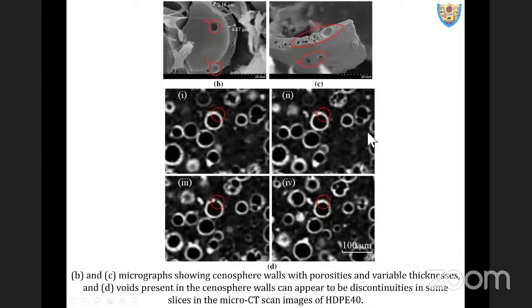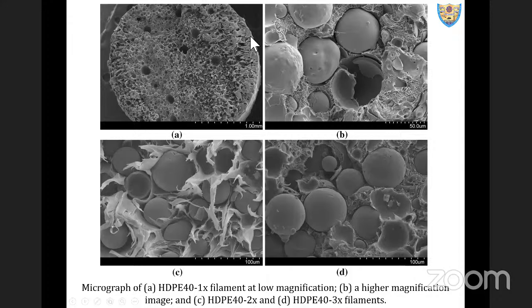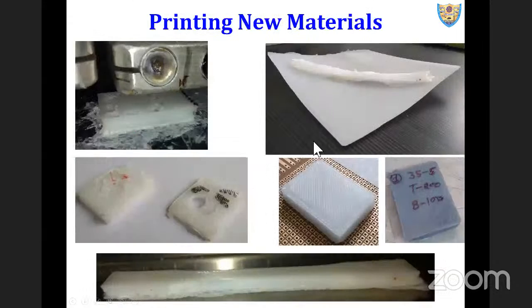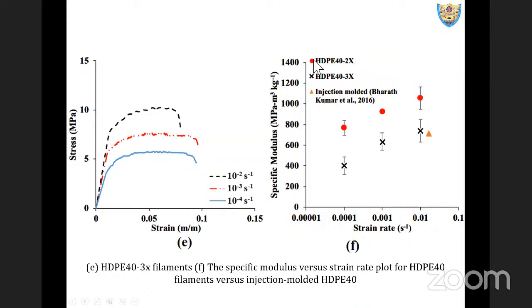Now, once you develop this filament, before jumping into 3D printing, you need to have a counter check. And that counter check we did here. We compared the filament, which is 2-time extruded and 3-time extruded, with the injection molded sample. Now, what do you mean by injection molded sample? It is 165 in length, dog bone type, strip type. So we have compared the filament which is developed with the full-fledged dense sample. And this is one counter check probably advisable before jumping into 3D printing after filament extrusion or filament development.